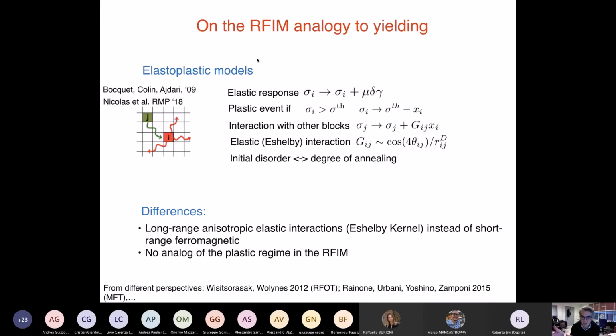In metallic glasses, the microscopic time scale is a picosecond. So if you have 1 hour at your disposal, you can equilibrate the system on time scales of order 10 to the 14 microscopic times. This means that when you prepare a metallic glass and then study its rheology, you are able to equilibrate the system on time scales much, much larger than for colloids, which are much larger than for foams and granular systems. Since you are able to equilibrate on much larger time scales, you have annealed the system much better, and in principle we expect the system to be locally much less disordered.